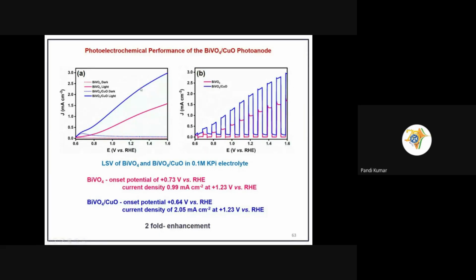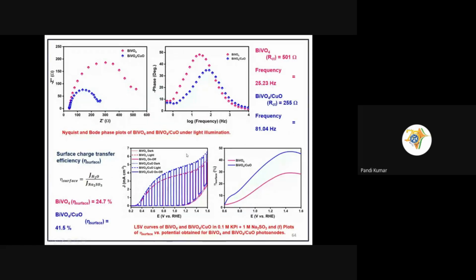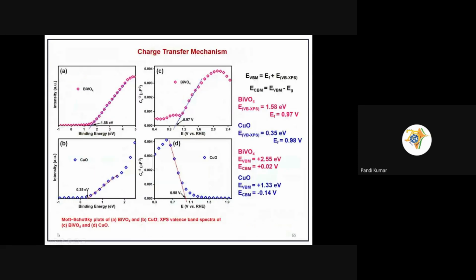In the previous case, we used powder samples, so we got a current response of 25 microampere, but here we are able to get 2.5 milliampere. It's almost 100 times higher than the previous one. After making this, the charge transfer separation property we also checked by chopping the illumination through linear sweep voltammogram. Then we want to see the surface charge transfer efficiency by adding a sacrificial agent into the supporting electrolyte. Then we performed this photoelectrochemical water splitting. Here we are able to see that after forming the heterojunction, almost double the increment in the surface charge transfer process. Then we want to derive the mechanism.